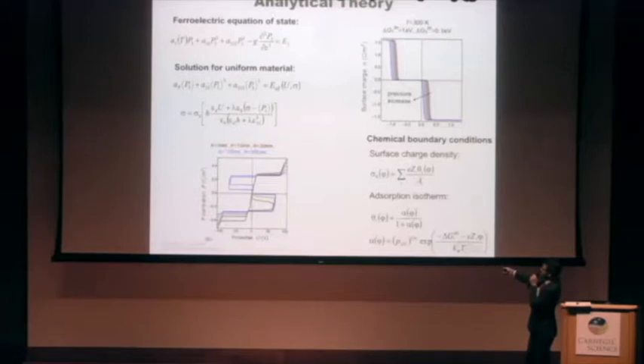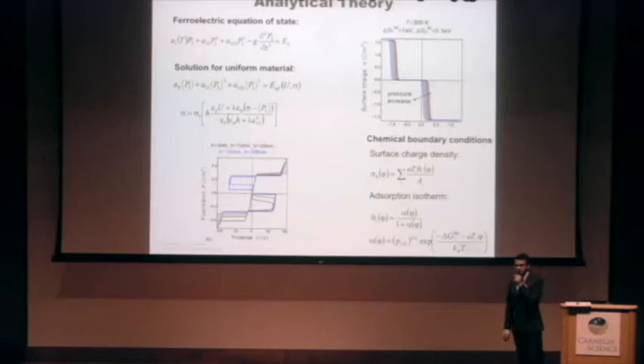It depends on the applied potential, which obviously has to be solved self-consistently. It depends on the charge of the ion and the area of the ion. And we say that it follows an adsorption isotherm. What this means is that the surface charge density is going to depend on your pressure of oxygen in the chamber, for example, as well as this delta G value, which is the energy of formation of a surface ion or defect. So you can think of this as the surface charge. As you change the pressure, you're going to change the surface charge density.